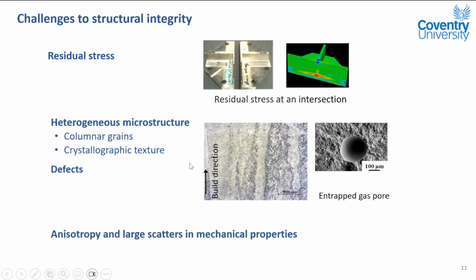So the problem of all of these is they do cause anisotropy in the mechanical properties. So the loading direction in the material direction or transverse to the direction would be different. So which design allowables would people use? And also they cause very large scatter, much larger than casting and wrought materials.